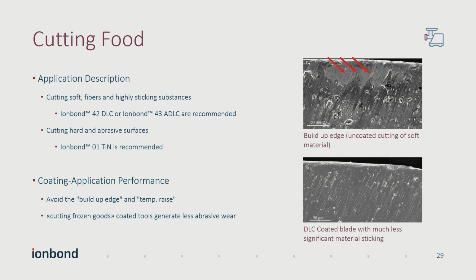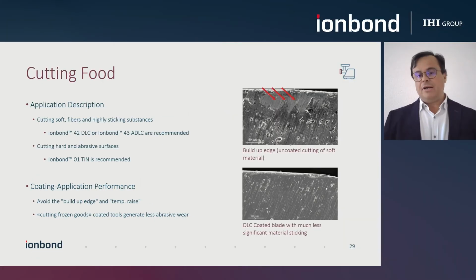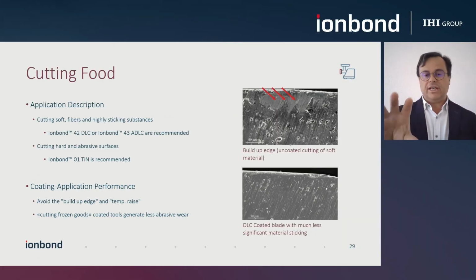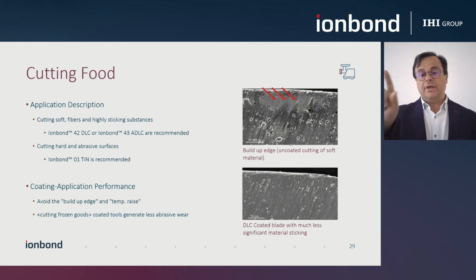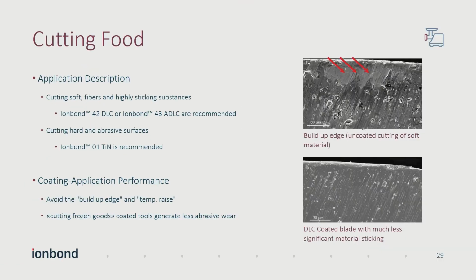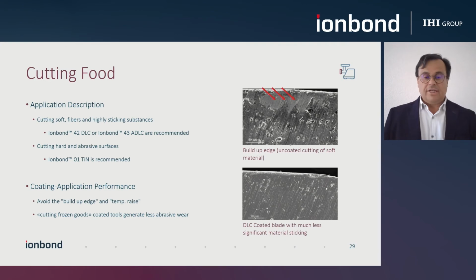So for the first, we really recommend the use of diamond-like carbon coatings to avoid what you see on this scanning electron microscope to the top right of your screen, which is really material being sticked. So by the use of diamond-like carbon coating, you can avoid this. And by avoiding this, you also avoid the temperature to raise, and you can have a cleaner cut. In the case of cutting abrasive goods, like for example frozen fish, you should use then the titanium nitride, for example, where you have a higher resistance to the abrasion for this particular application.